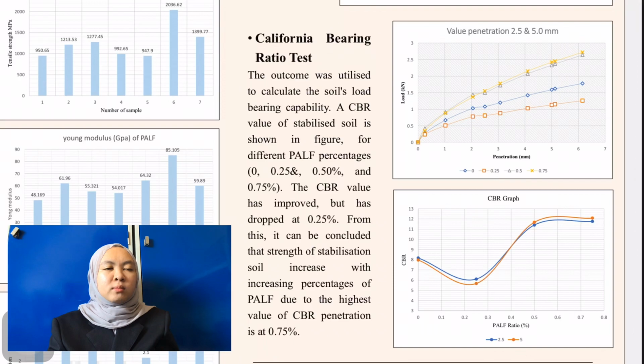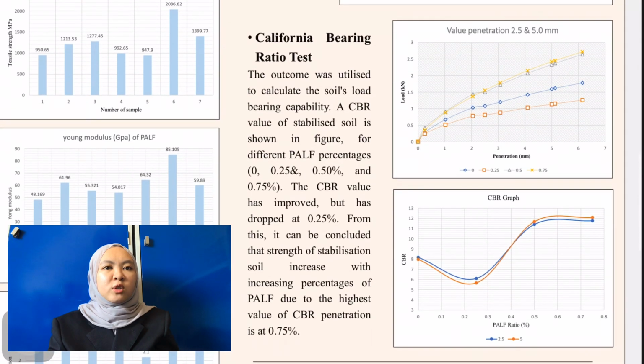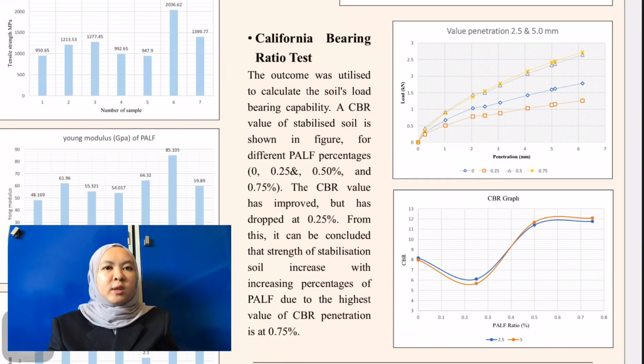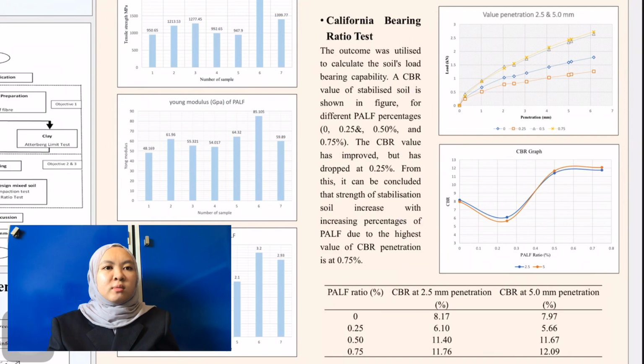The graph represents the relationship between plunger load and penetration at various fiber percentages. The CBR values are obtained for the load corresponding to the 2.5 mm and 5.0 mm penetration, as summarized in the table. And the larger value is commonly used as the CBR value. The result revealed that the CBR value at 2.5 mm penetration is greater for 0 and 0.25%, while for 0.5 and 0.75% it is greater at 5 mm penetration.